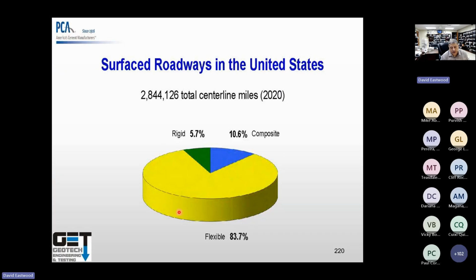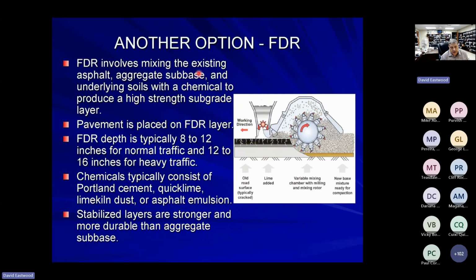The application: basically 83% of the pavements in the US are asphalt. 5.7% is concrete. 10.6% is a combination of asphalt and concrete. FDR involves mixing up the existing asphalt aggregates, subbase, and underlying soils with chemicals, in this case cement, usually like 7% cement. It goes in there and chops the existing pavements into small pieces, and then you mix that with cement, and that becomes your base. Typically, chemicals consist of cement, quick lime. I don't think lime works real well.